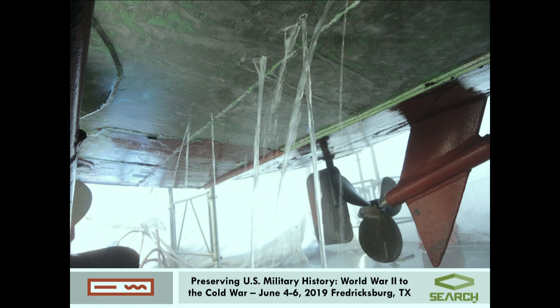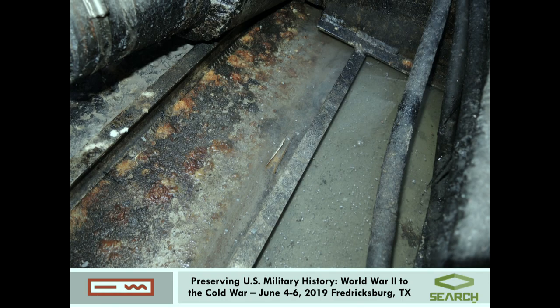I mean, not necessarily due to the water jetting, but just due to the fact that this boat had been placed outside for many years, and corrosion in the bilge was quite extensive. And so it revealed all those holes in the hull. And of course, it didn't take long for us to understand that it was related to the area of the bilge where dirt and water collects and create a corrosion line.